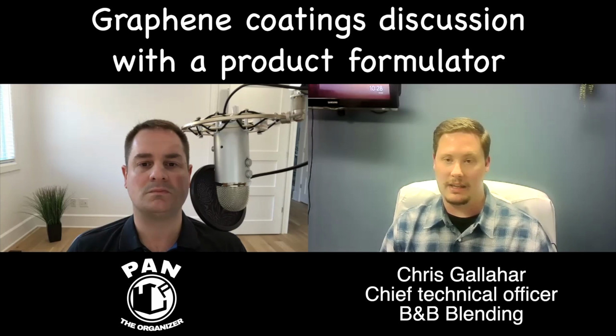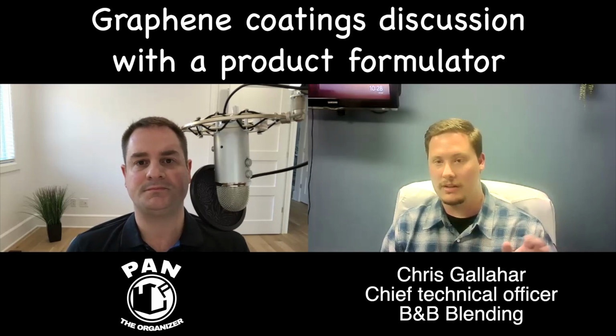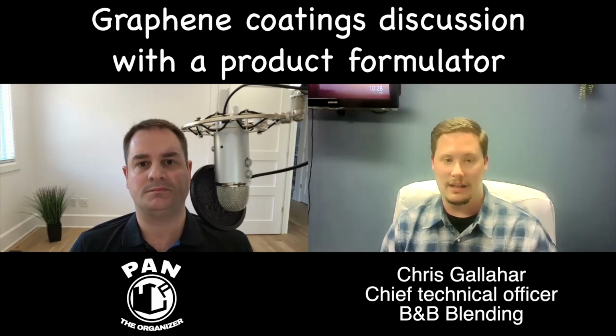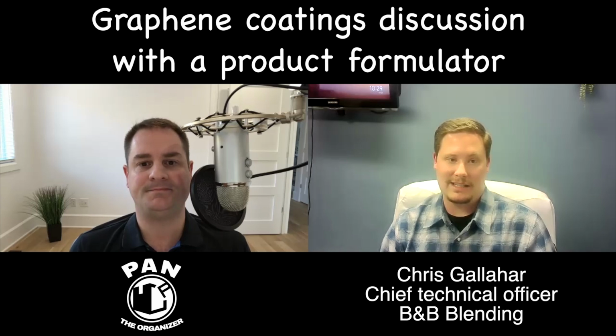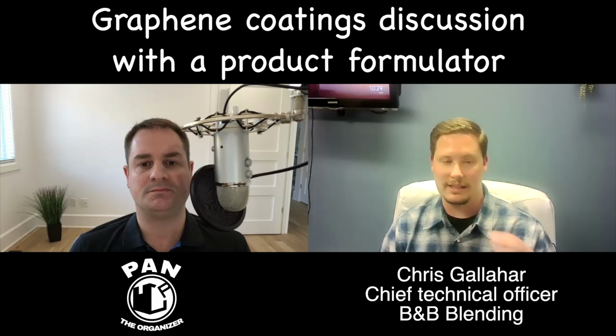Our previous quartz coatings were best understood to be basically a polysiloxane, right? And that could be a perhydropolysiloxane, which means it's all hydrogenated. It could be something like an organopolysiloxane, which usually will have some methyl functionalities on it. So those are CH3s. Those essentially act as contaminants. They don't allow cross linkages and stuff to occur. You can fire the coating film to try and drive those things off in the form of methane and get additional cross linking and curing.